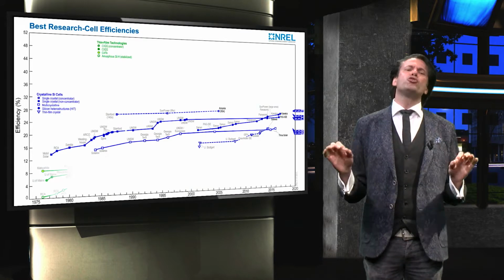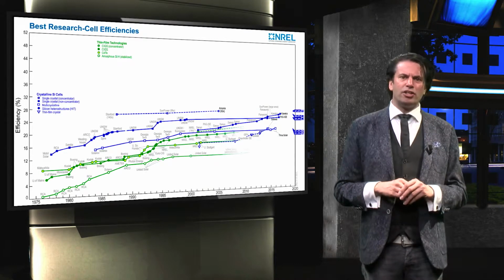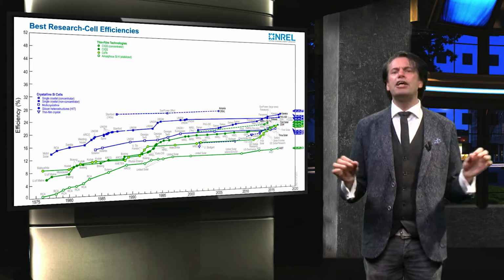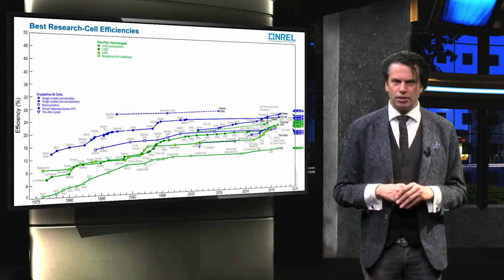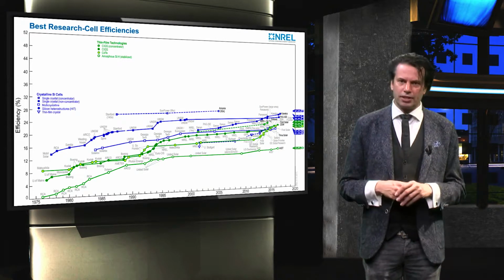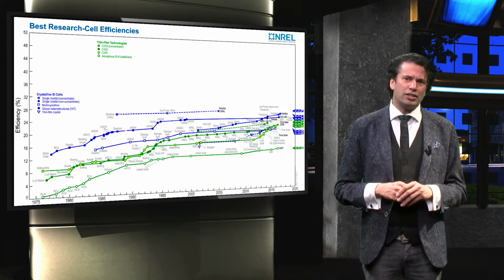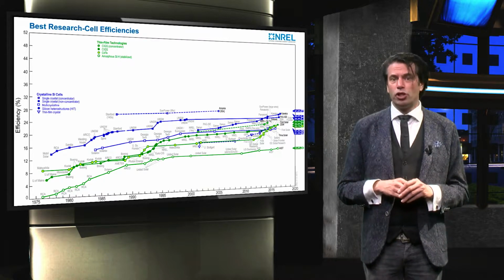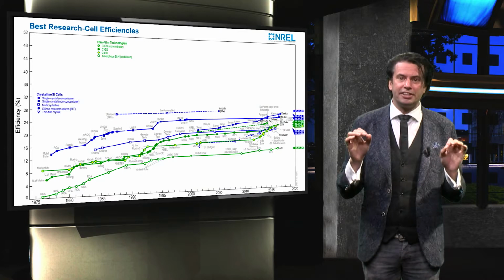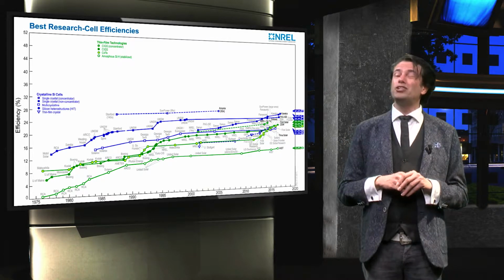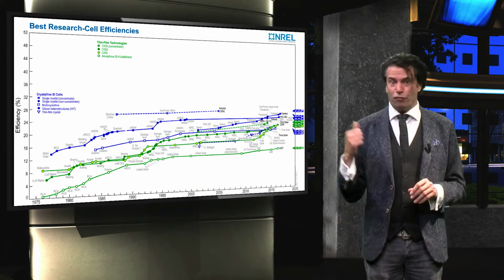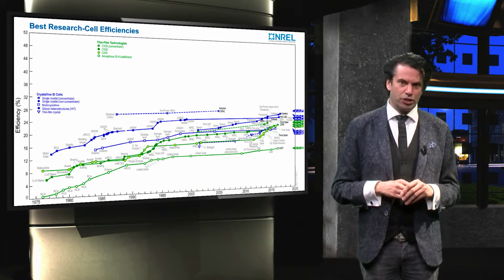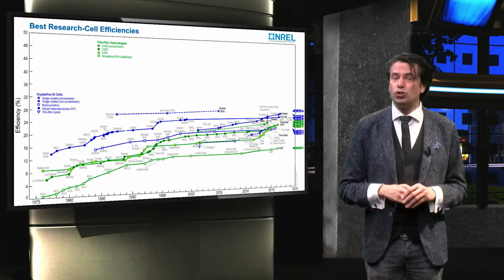If we focus on the most important thin-film PV technologies, we see that the record stabilized efficiency for thin-film silicon PV equals 14.0%. The PV cell was based on an amorphous silicon, nanocrystalline silicon triple junction processed at AIST in Japan. ZSW in Germany has set the world record for the CIGS PV devices with an efficiency of 22.6%. First Solar is responsible for the world record for thin-film cadmium telluride PV technology. This record equals 22.1%.